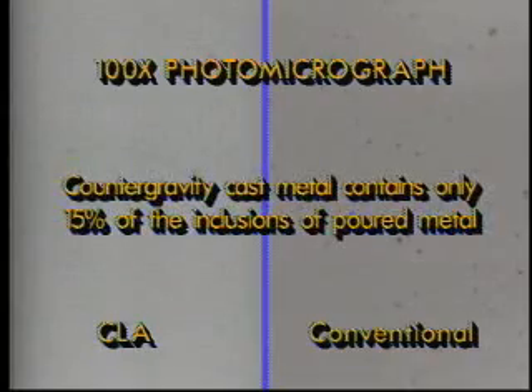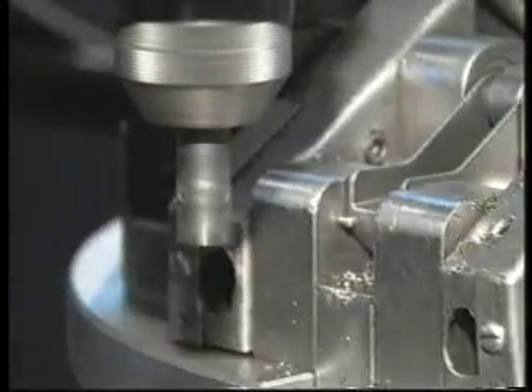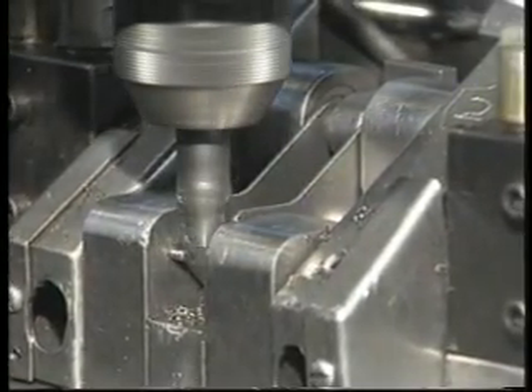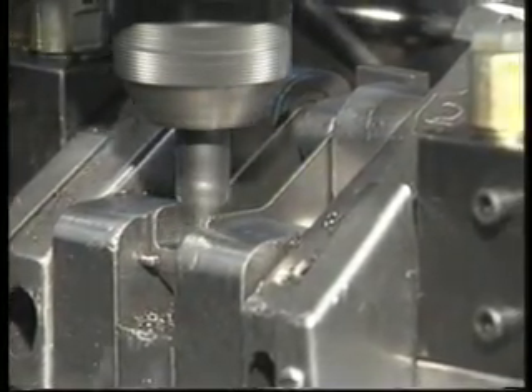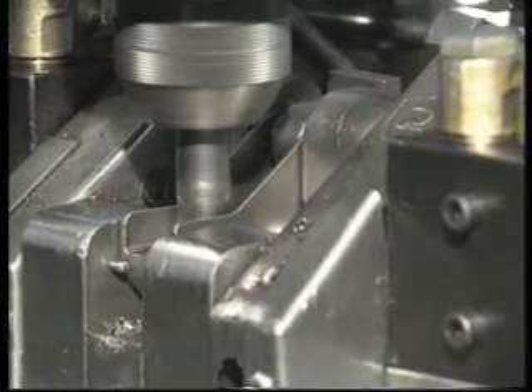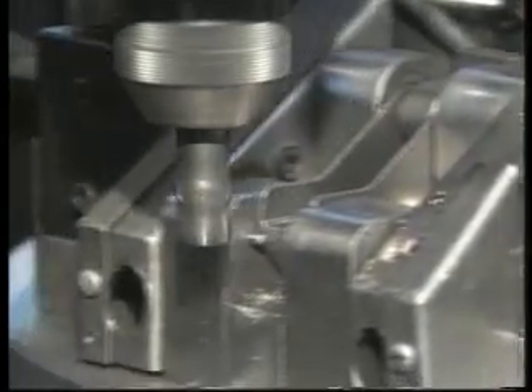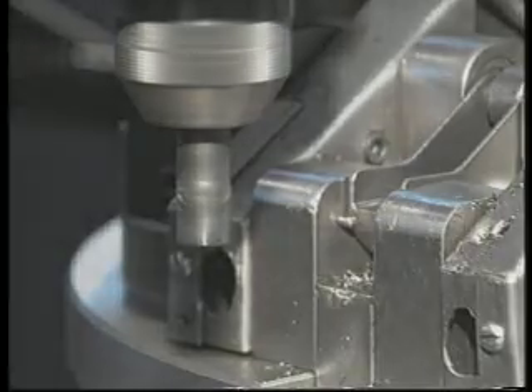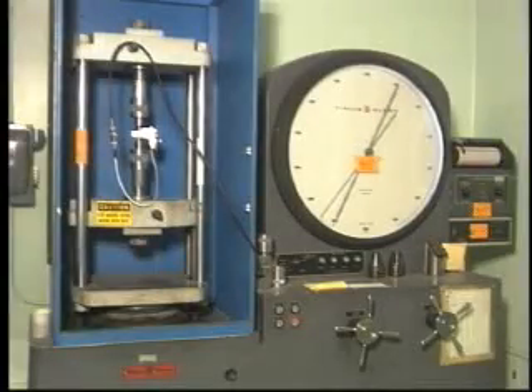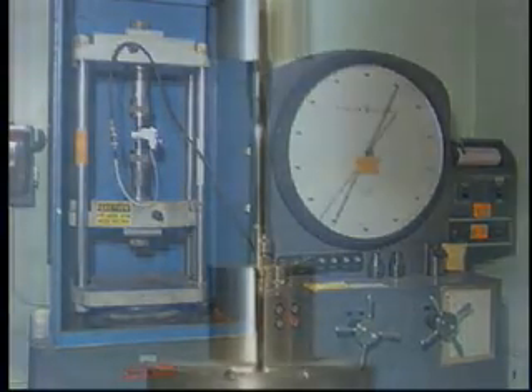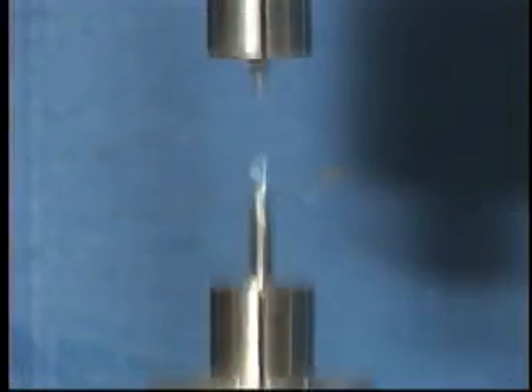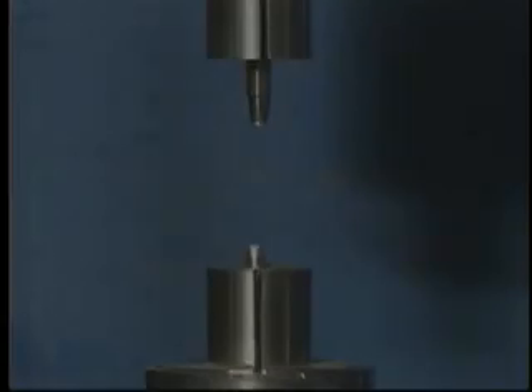Typically, countergravity cast metal contains only 15% of the inclusions of poured metal of the same analysis. This cleaner metal has been shown to reduce tool wear in comparative machining tests done under controlled conditions, giving increases in the life of cutting tools from 100% to 500% depending on the alloy. Inclusions are not merely nuisances for production to battle. They can cause premature part failure by serving as sites for initiation of fatigue cracks in highly stressed parts, even though they may not be detected visually after processing.